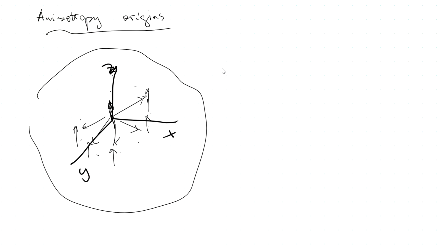at any location X, Y, Z, we will have a magnetic moment that interacts with our magnetic moment at the origin. Then the interaction energy would depend only on the distance between this moment and the other one. So here's R, this is another magnetic moment here. So there are two of them. This is the distance R. So what it means is that there is no angular dependence. And since there is no angular dependence in interactions between magnetic moments, there is no anisotropy.